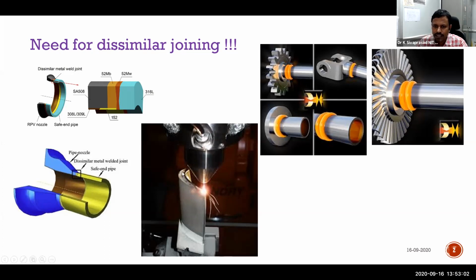Shape, repair weldability. The shape and contour, everything should be studied. When you want to do this repair weldability, people sometimes used matching filler or some inferior filler. And the moment you are using any welding, even mechanical engineers are very well aware that welding is nothing but localized casting, and you will never get strength equivalent to the base metal. It is very, very difficult. In a very idealistic case of TIG welding, it will be very difficult to get 60% efficiency compared to the parent metal. So it's not just joining alone.